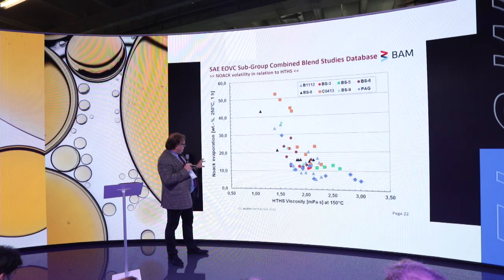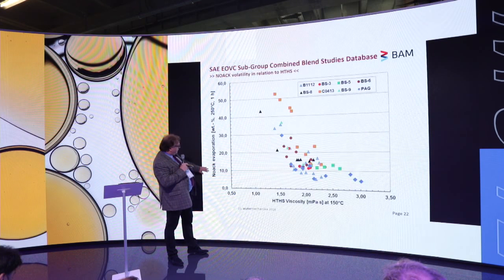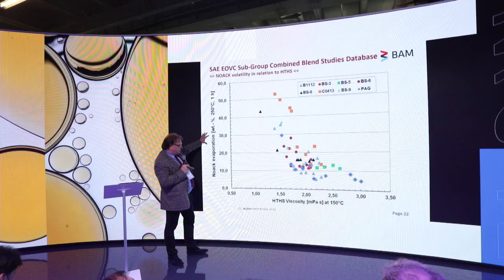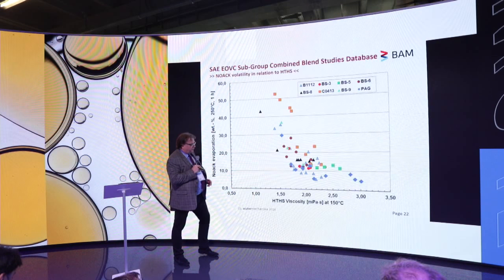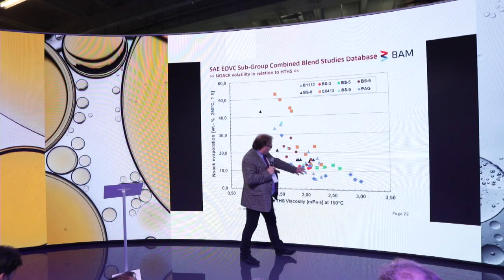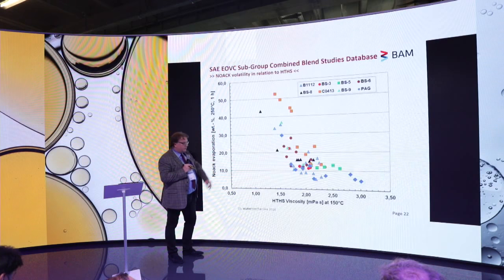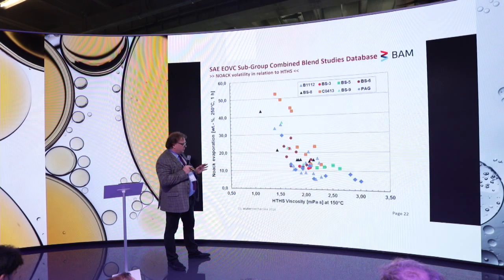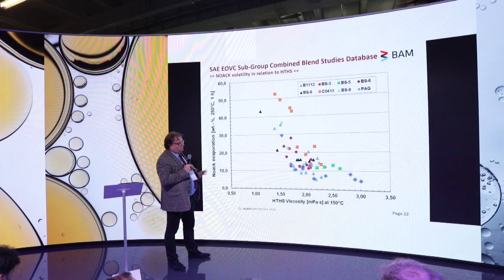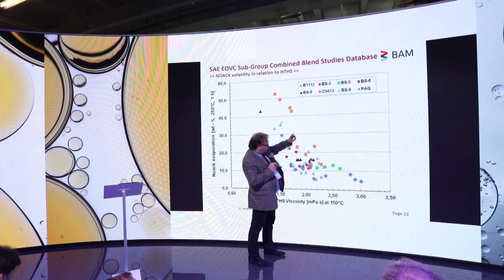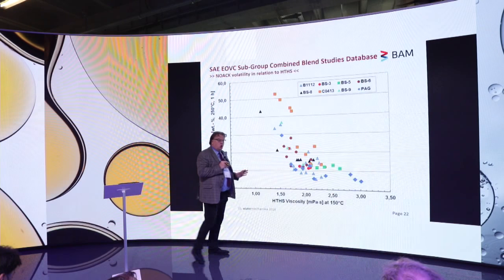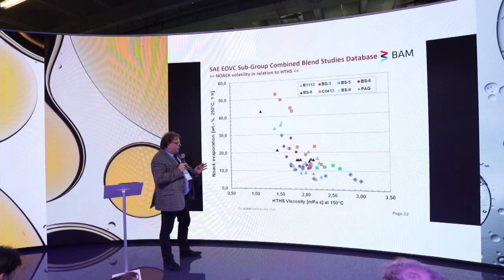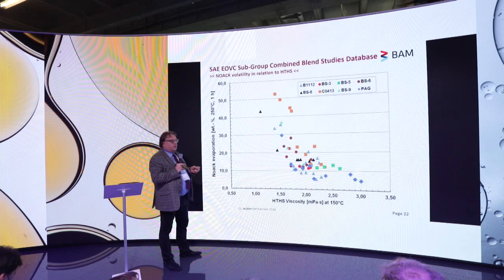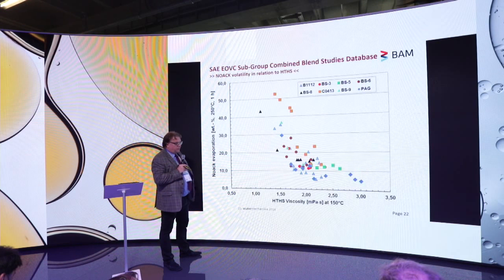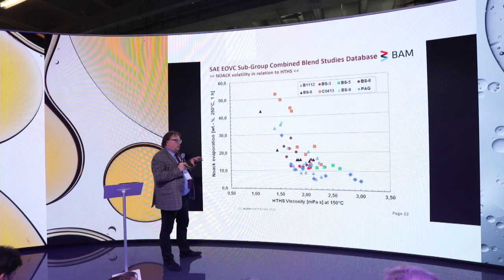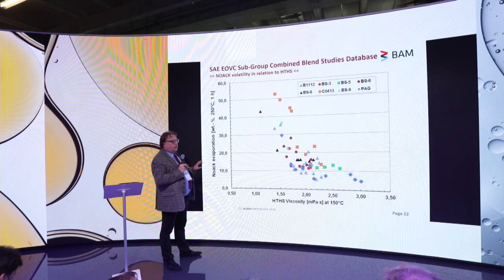One problem with low viscosity engine oils, you have here the NOACK evaporation, it's the physical evaporation, and here the high temperature, high shear viscosity, and what you see is, the lower the viscosity, suddenly the evaporation goes up. It means for normal engines there will be a limit. I would say 16, maybe 12 when you use polyglycols, because the PAGs, they have on average the lowest evaporation rate. So in consequence, if you want to go to very low viscosity engine oils, you can no longer stay in hydrocarbons for normal engines, not for range extender, not for hybrid systems.